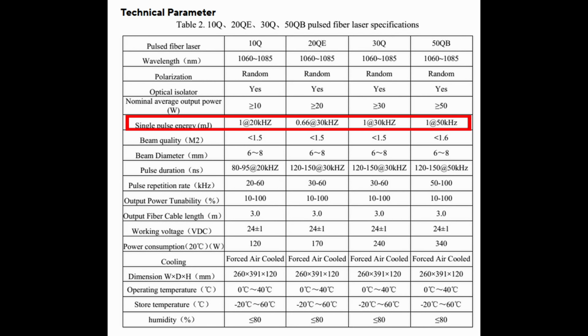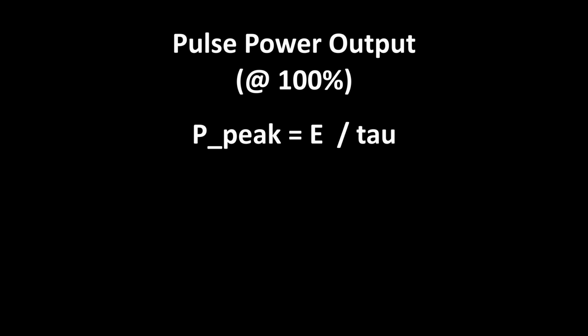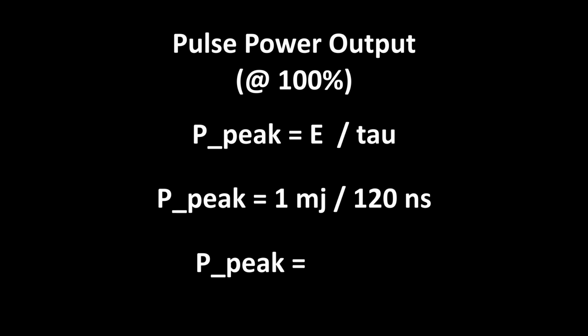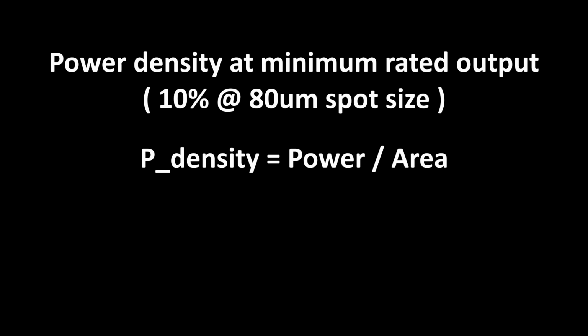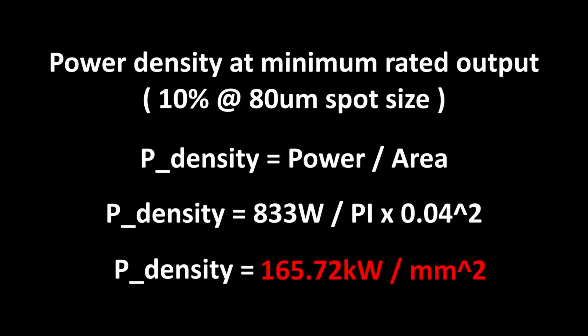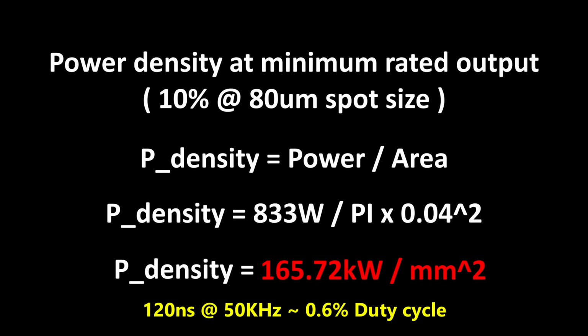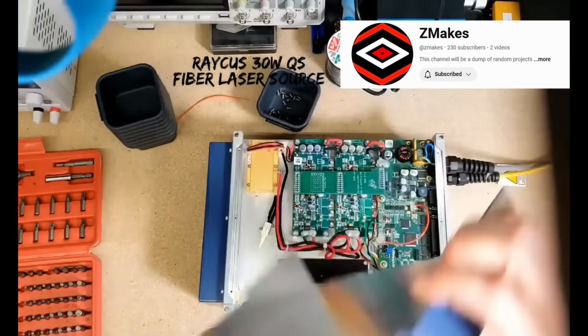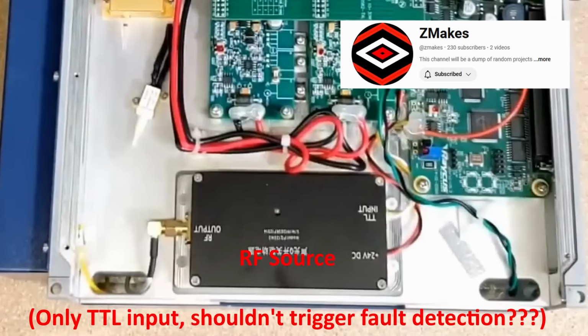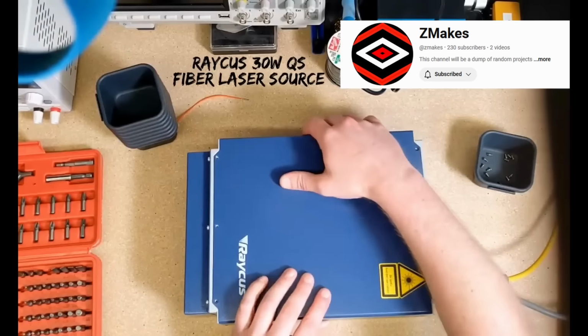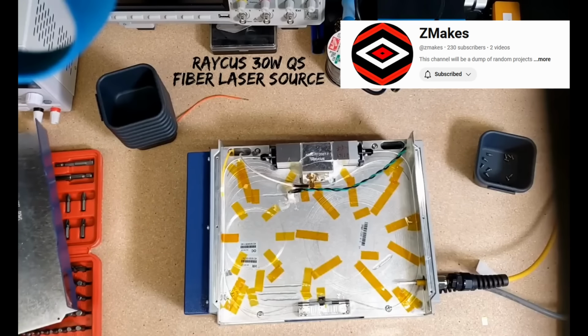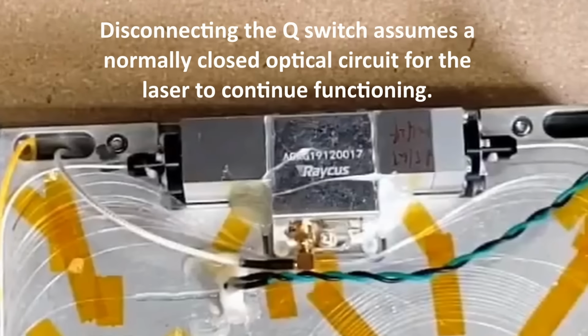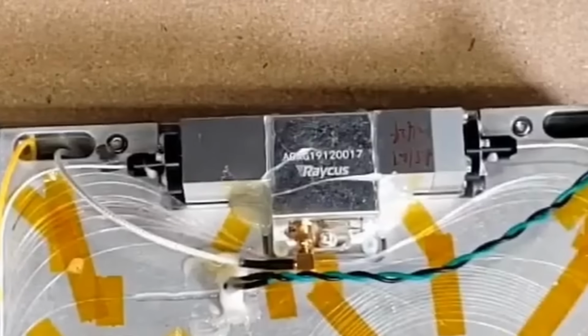The major feature that pushed me away from these, however, is the integrated Q switch. This is a great feature for allowing the laser to achieve much higher peak intensities, which is perfect for ablating metals. But in the context of fusing metal powders together, depending on the characteristics of the powder itself, my impression was that this would vaporize the powder to be formed into a solid, and potentially disrupt the surrounding powder. There may be a solution to this, which is to simply unplug the Q switch, perhaps needing a dummy load to fool the electronics. But I was unsure of how the device would actually respond and conscious that it might just result in some expensive magic smoke, so I went for an alternative.